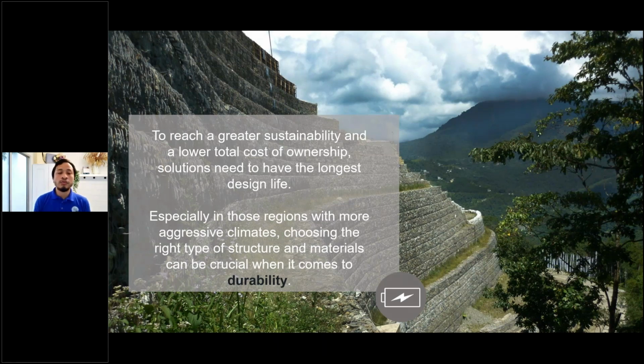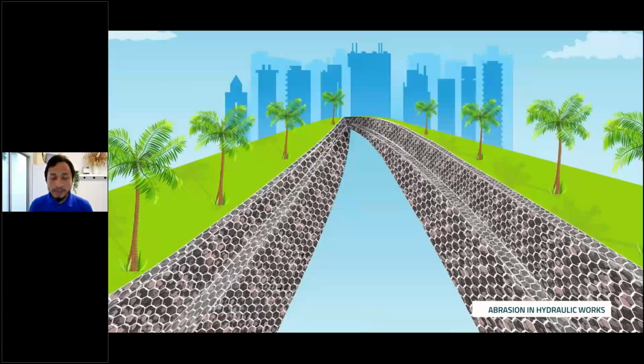Now, when you also talk about the durability of one of the sustainable solutions, gabions, one of the issues that you normally encounter is the corrosion on the gabion. What happened here is because the coating is actually the line of defense for the gabions. So once the coating is exposed, the base metal is exposed to atmospheric condition, and we start to have corrosion. And when you have corrosion, you will have this issue with tearing of the gabions, and eventually this rock fill in the cage will just wash out into the river.